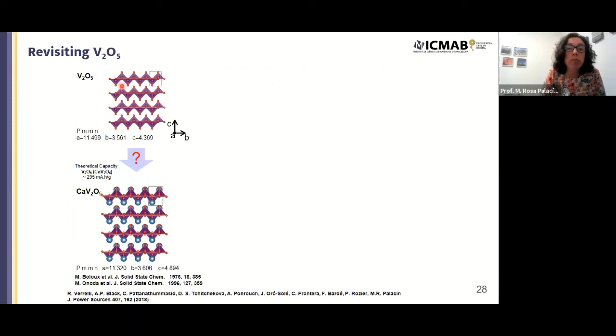This is the crystal structure of V2O5. And interestingly, there is a compound that has been reported and prepared by solid state synthesis, CaV2O5, which has a very similar crystal structure. So we naively thought that we could electrochemically intercalate calcium in this compound very easily.